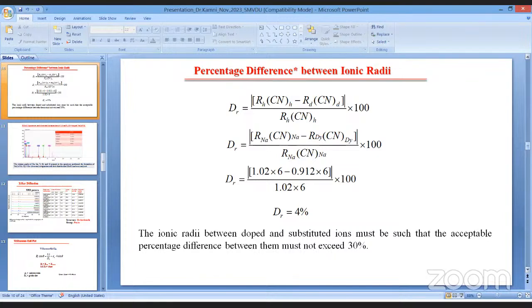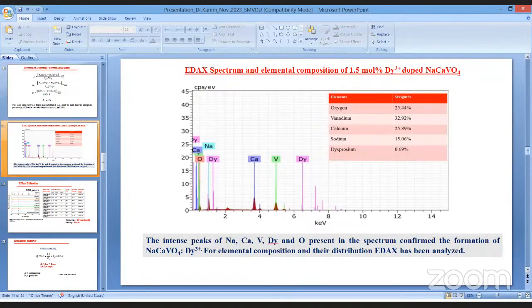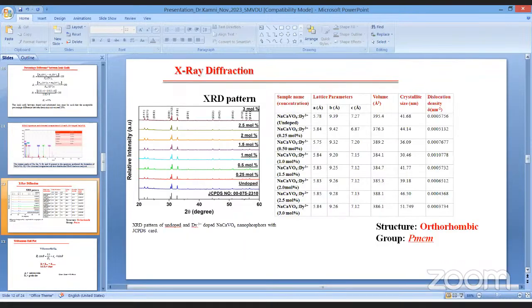So we see that the percentage difference of ionic radii between the sodium and the dysprosium ion is less than 4%, so we have decided that our dopant ion will substitute the sodium ion in the sample. The second is the EDS spectra. The intense peaks of sodium, calcium, vanadium, dysprosium, and oxygen present in the spectrum confirm the formation of NaCaVO4, which is doped with dysprosium. For elemental composition and their distribution, EDX has been analyzed.